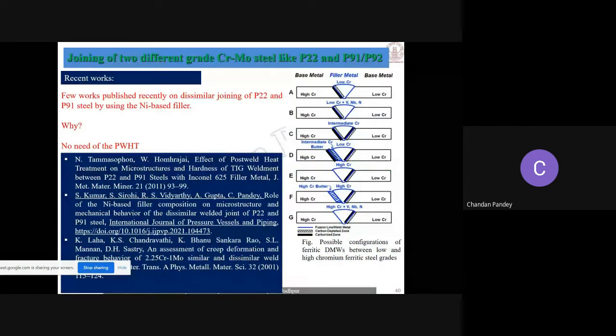So how can we minimize that type of problem, especially if you talk about the P22 and P91 steel? In some research, the application of nickel based filler has been proposed. Why are we going for nickel based filler? Generally, nickel based filler solidifies in austenitic mode, and the end structure of that weld metal will be austenite. So if the end structure is austenite, it doesn't require any post weld heat treatment.